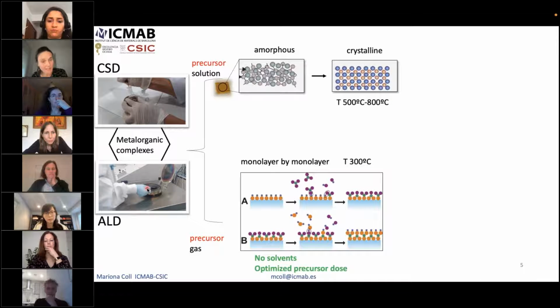We also use atomic layer deposition. In this case, we use metal organic complexes in a gas phase. For a complex oxide, we alternately pulse these complexes in a vacuum chamber. These metal organic complexes react in a self-limiting manner with our surface, and this enables us to have nanoscale control in terms of composition and thickness. What is really interesting is that we can work at very low temperature, which is compatible with CMOS technology.